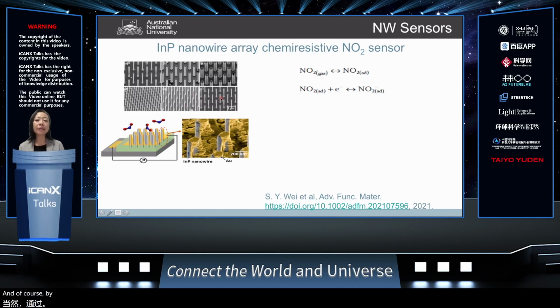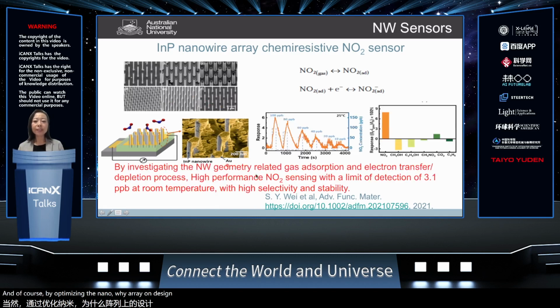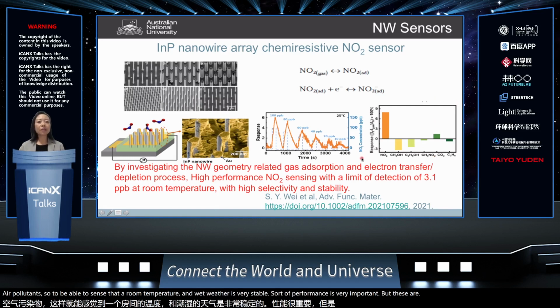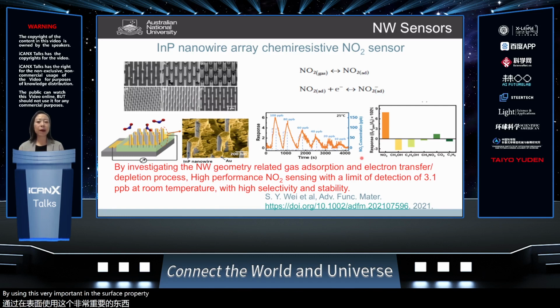And of course, by optimizing the nanowire array design, we demonstrated very high performance room temperature nitrogen dioxide sensing with a limit of detection of only 3.1 ppb at room temperature. It also has very high selectivity to nitrogen dioxide compared to other commonly used gases and pollutants. We know that nitrogen oxide is a very common air pollutant, so being able to sense it at room temperature with very stable performance is very important. This gives us a very interesting direction to look at, using the surface property as well as the one-dimensional nanostructure property for gas sensing.